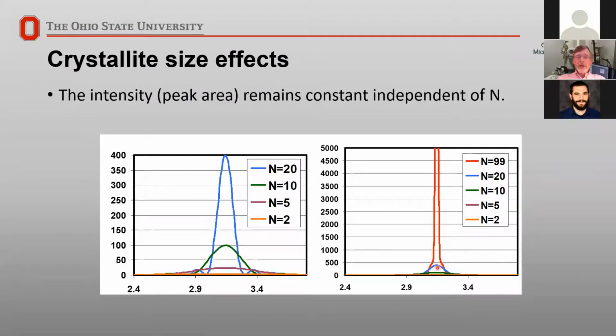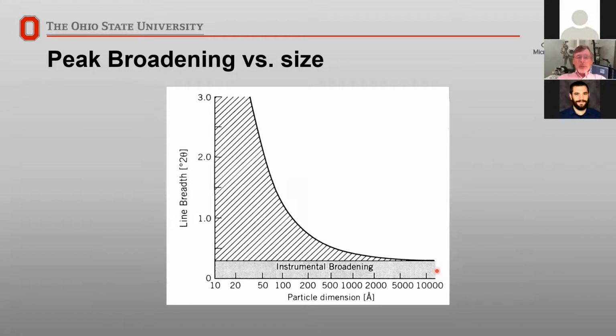Now, the area under the curve is remaining the same. It's just that it's now all compressed into one angle. So we can now take this information and use it to estimate the size of the crystals that we have in our sample. So we have a certain amount of width in our peaks due to the instrument itself. That's our instrumental resolution. But once we get down to below somewhere around 200 nanometers, in this range of, say, 3 to 5 up to 200 nanometers, we can use this broadening to estimate the size of the crystals.